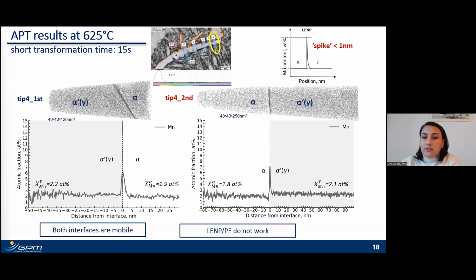However, there is another point that can be highlighted. We clearly observe that the manganese composition is different in ferrite and martensite, previously austenite, and this is not expected under the LENP condition, because the compositional profile on both sides of the interface is supposed to be equal.